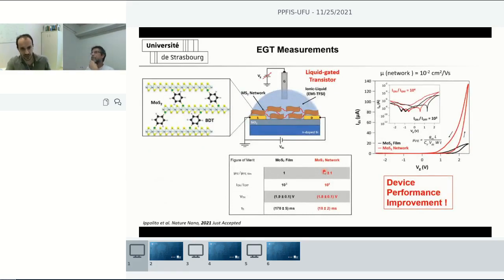So here we are, the solution gate transistor or electrolyte gate transistor. To probe the electrical properties of these films and networks, we use this kind of device because it allows us to probe more easily the accumulation of carriers at the interface with the electrolyte than the interface of the silicon dioxide. And what we observed here is the transfer curve of the transistor for the two cases. In black, we have the transistor current for films, while here in red, we have the transistor curve for networks. So there is a clear improvement of the performance by 1 order of magnitude.